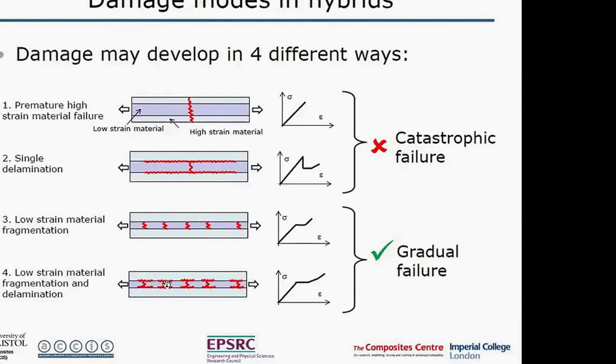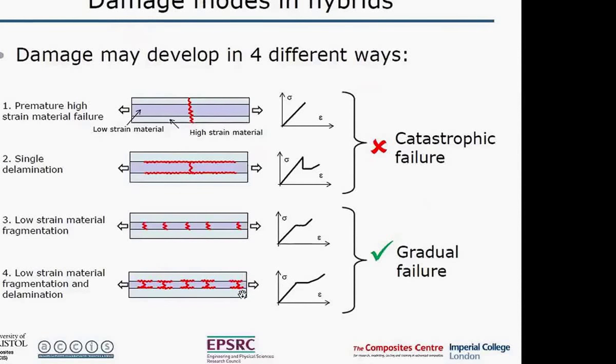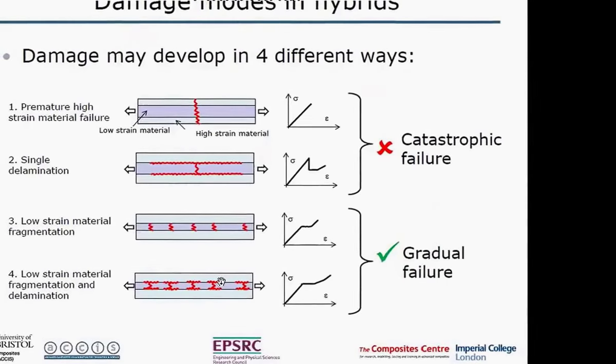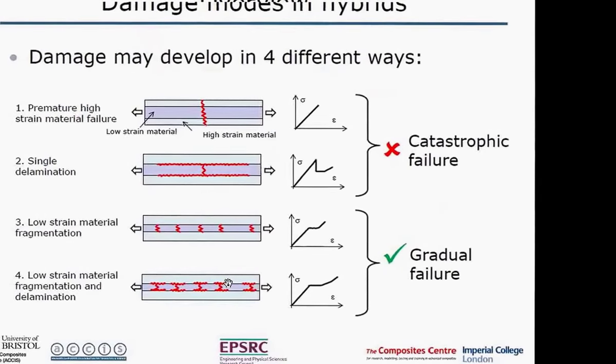And in some cases, accompanied by a little bit of localized delamination. And that gives you this plateau on the stress-strain curve and this gradual failure as a result of this fragmentation which is taking place within the carbon. So that's the sort of mechanism we want, this plateau on the stress-strain curve, and we can achieve that by the right combination of properties to get that fragmentation behavior.